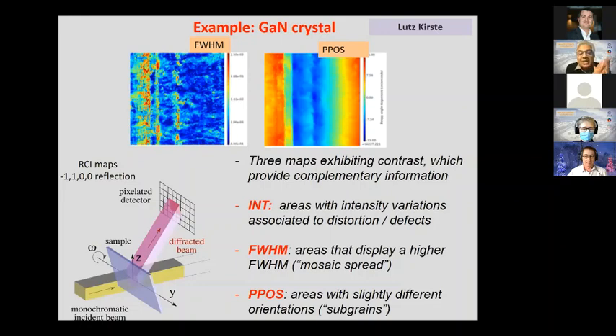Let's go to the example of a gallium nitride crystal. Well, the integrated intensity map corresponds more or less to what you can have on the laboratory source or using wide beam. In the integrated intensity map, you have areas with intensity variations associated to the distortion defects.